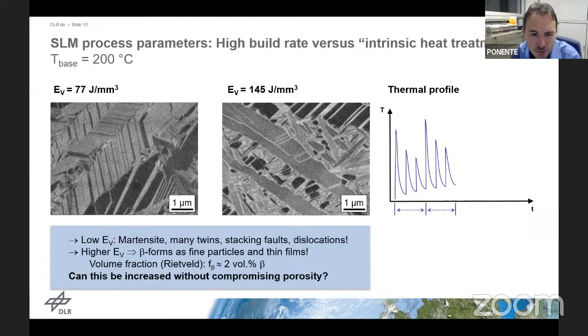This is very typical for SLM titanium materials at low volume energy densities. On the right-hand side, you see the parameter set corresponding to the right-hand side of the parameter window, which looks already a bit different. You see these brighter borders in between this martensite lath and alpha prime grains. So going to higher process windows already gives you a different microstructure.